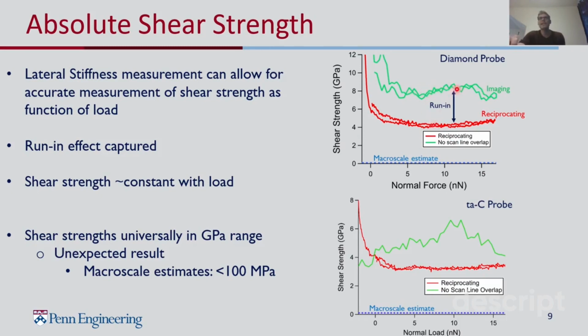So that's indicating that this run-in process drives down the shear strength as we expected based on the results of the last slide. And so this run-in process gives you a lower interfacial shear strength. Additionally, what we see is that the shear strength is approximately constant across the entire normal force range. And that's true with both probe materials and both imaging techniques. And that'll become relevant later on in the talk, so I'll talk a little bit more about that.